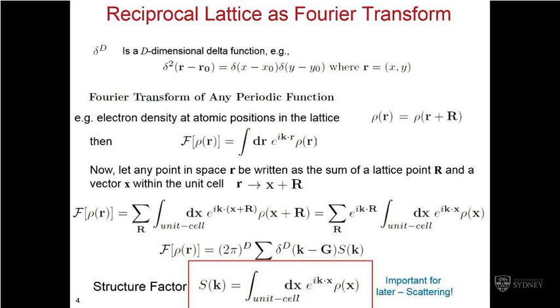We have, again, the d here represents the dimension. D is 1 for 1 dimension, 2 for 2 dimensions, 3 for 3 dimensions. This exponential term, remember, boiled down to a delta function such that k must equal a reciprocal lattice vector, otherwise it's 0. And we are calling this expression here S. So this is called the structure factor, S, and it's equal to this here. And we're going to do an example of that later on in the lecture today, and you'll get familiar with the form of it.